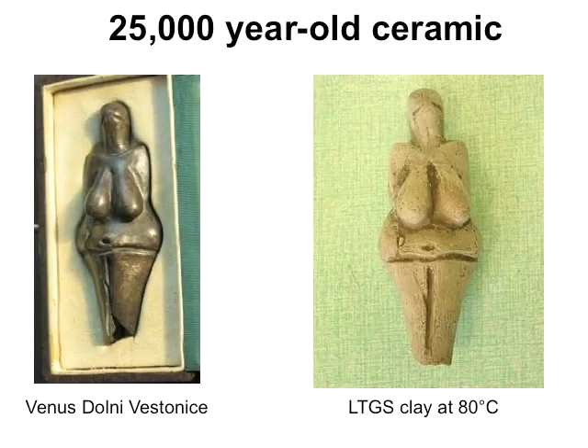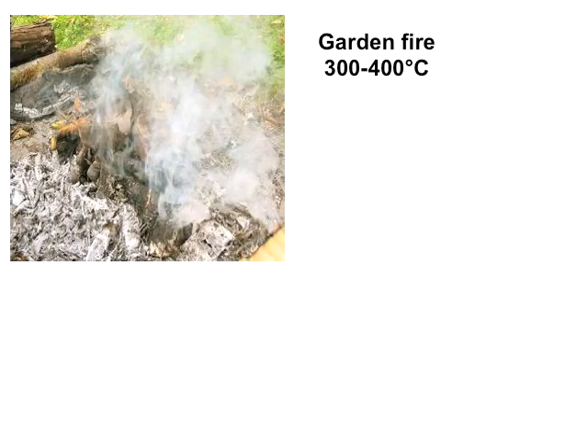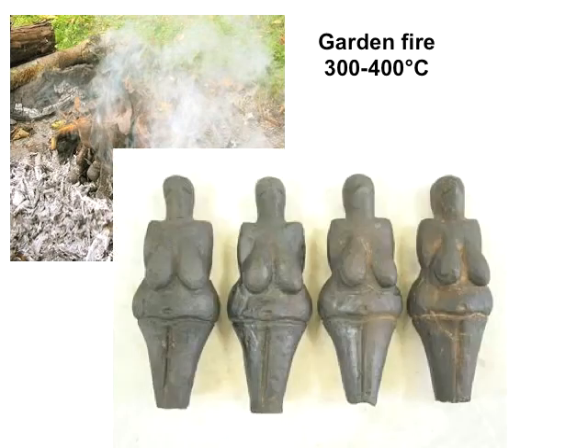Well, very easy. We have replicated it, dried at 80 degrees C, put it in a garden fire in a reducing atmosphere, 300 to 400 degrees C, and we got our Venus. This is how it has been done, provided the chemistry is in place, and the chemistry is very easy to achieve with ashes, with clays, with salts that are commonly found in clays and so forth.